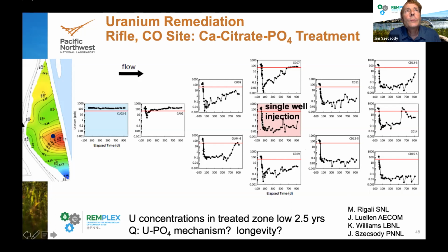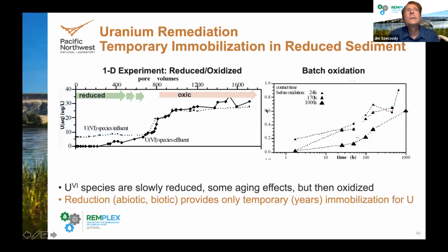What you see is the uranium concentration dropped about 3 orders of magnitude in the injection well and has stayed pretty close to there. Some of the slightly up gradient wells had low uranium concentration, and they're starting to come up. But you can't tell exactly what the uranium retention mechanism is just from the aqueous uranium concentrations. One needs solid phase analysis from cores. There probably are uranium phosphate precipitates formed, but because there's also reduction in the system, that can be a temporary retention mechanism, which is what I'm showing on these 2 diagrams. These are separate experiments, not with Rifle sediment. It's just with a Hanford sediment that was initially reduced. This is a column experiment where uranium is injected, and here's the effluent uranium concentration.